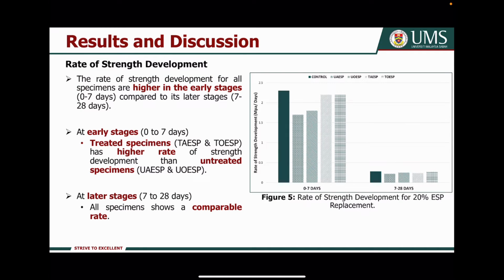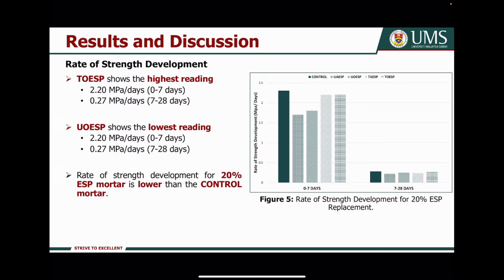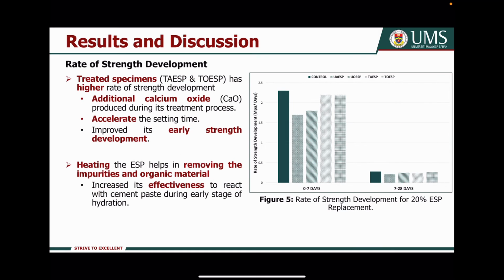For the rate of strength development, as you can see in the figure, the strength development for all specimens is higher in the early stage, but at the later stage, all specimens show a comparable rate of strength development. Nevertheless, the rate of strength development for the ESP mortar is still lower than the control mortar. Next, the treated specimen has a higher rate of strength development because of its additional calcium oxide, which accelerates the setting time and improves its early strength development. Meanwhile, heating the ESP helps in removing the impurities and organic materials, which increases its effectiveness to react with the cement paste.